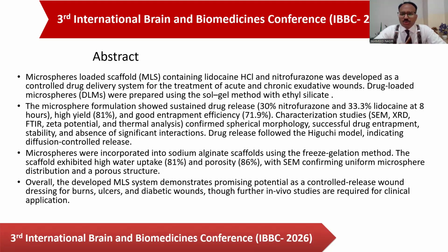Microspheres prepared showed a very good drug release, and characterization studies showed very good morphology, drug release, entrapment efficiency, and most importantly, the drug release followed the Higuchi model. And microspheres were then incorporated into the sodium alginate scaffold. Sodium alginate is very useful for exudative wounds, the wounds which contain blood and exudates. Actually, it swells up when in contact with liquids like exudate. So this project showed very good properties for exudative wounds, like hemostatic effects.